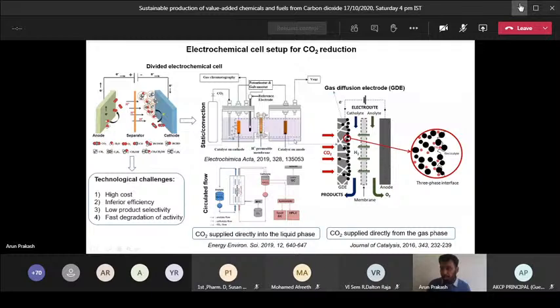And how you can make these electrodes, like freestanding carbon support? Because you are using the gas, this gas has to pass through your electrode surface. When you have a porous electrode, the gas can easily pass through the pores and it can increase your efficiency. For example, this is the carbon nanotubes. Everyone knows about different carbon materials like carbon nanotube and graphene. These are the 1D and 2D materials. If you use the carbon nanotube, you can arrange it in a pillar-like structure, something like how we build a house, right? If you use pillars in your house, it can add strength or stability to your house. Similarly, if you have a pillar-like nanomaterial structure, it can add strength or stability to your structure. Also, it has a lot of pores, so the gas can easily diffuse through the pores. So that is the idea of creating this carbon support.